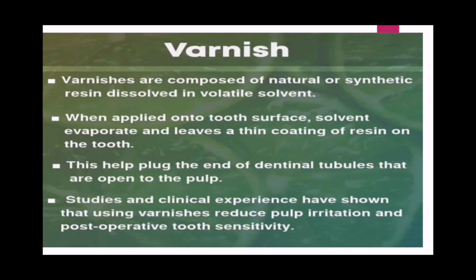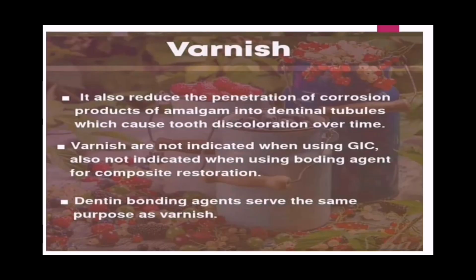Varnish. Varnishes are composed of natural and synthetic resin dissolved in a volatile solvent. When applied onto the tooth surface, the solvent evaporates and leaves a thin coating of resin on the tooth. This helps plug the ends of the dentinal tubules that are open to the pulp. Studies and clinical experience have shown that using varnish reduces pulp irritation and postoperative tooth sensitivity. It also reduces the penetration of corrosion products of amalgam into the dentinal tubules, which cause tooth discoloration over time. Varnish is not indicated when using GIC, and also not indicated when using bonding agents for composite restoration. Dentin bonding agents serve the same purpose as varnish.